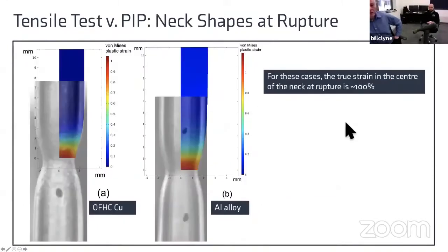But there are a number of issues, and you need to be confident you're capturing what goes on rather accurately. Another thing you can compare, if you want to, is the way the neck develops. Obviously, you can do this to some extent via the stress strain curve, but also you can look at the shape of the neck. So this is for a couple of different materials. One is copper, another one is aluminium alloy. Different stress strain curves, of course, different true stress, true strain curves. So when you do the simulation, you can compare not only the stress strain curve that you measure, but also the neck shape. And you can monitor how the strains are developing.